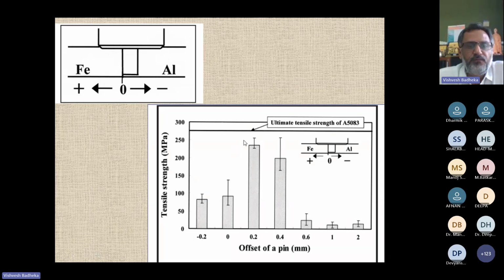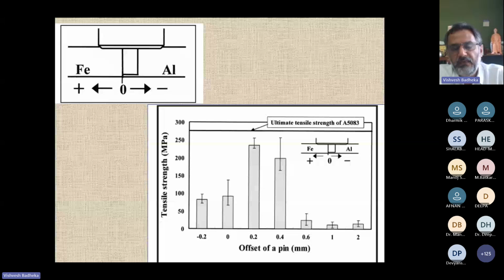Then if you go further beyond 0.4, it has gone down. If you go to 0.6, further gone down. 1 and 2, very fragile joints. You don't have strength. You can see that a minor variation in the offset from 0.4 to 0.6 has significantly affected the strength of the joint. So through this example I'm trying to explain to you that the offset plays a very, very important role for a given material combination, and the positioning of the material is also very, very important, right?